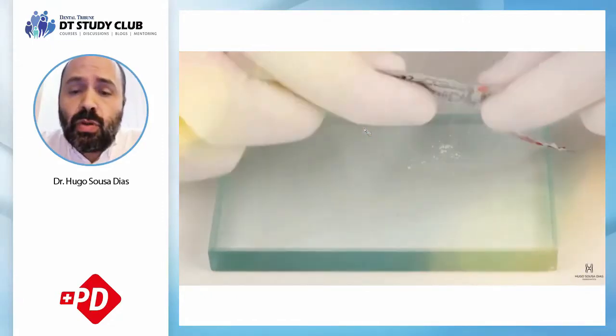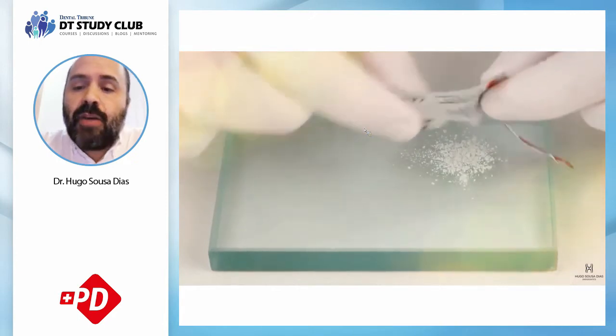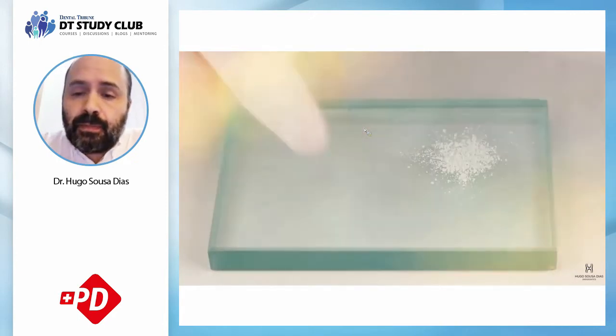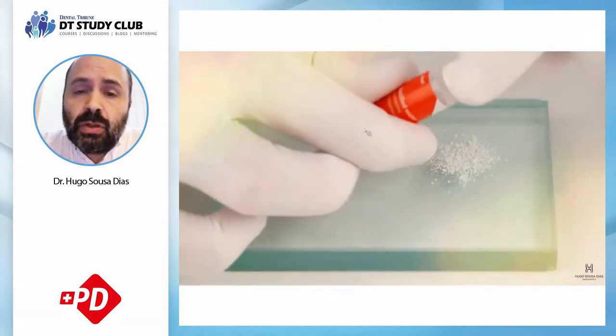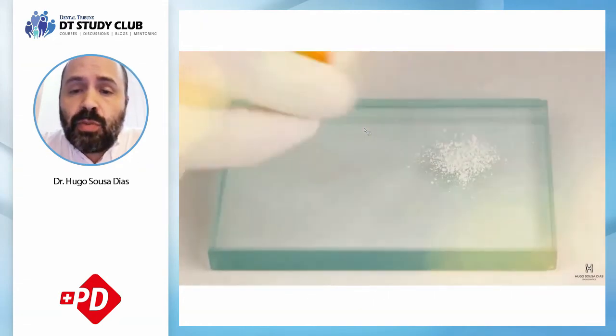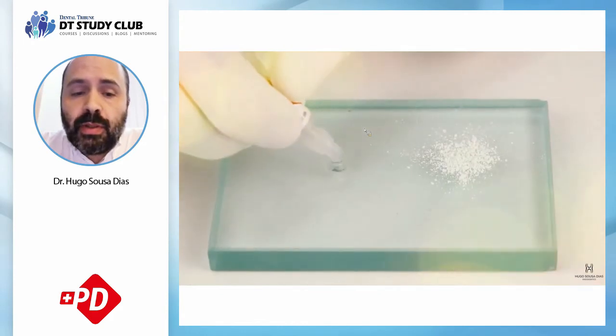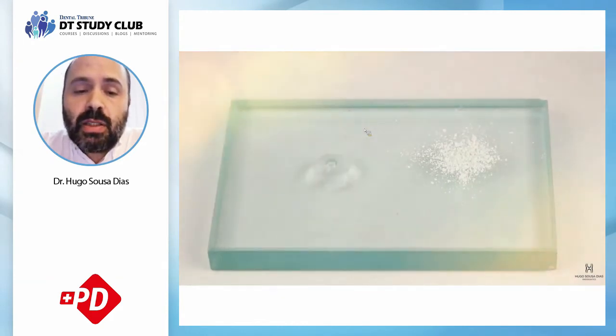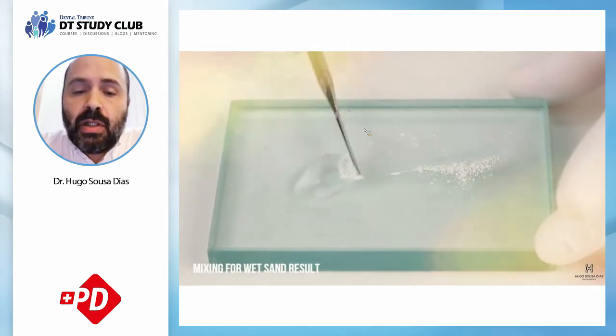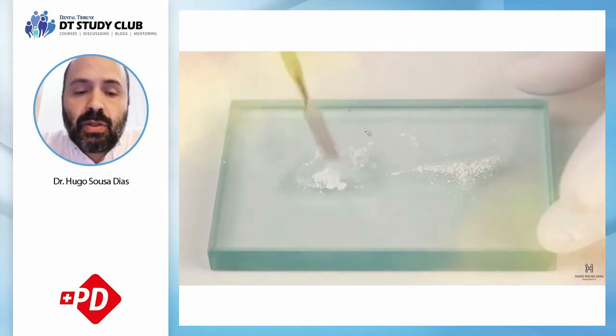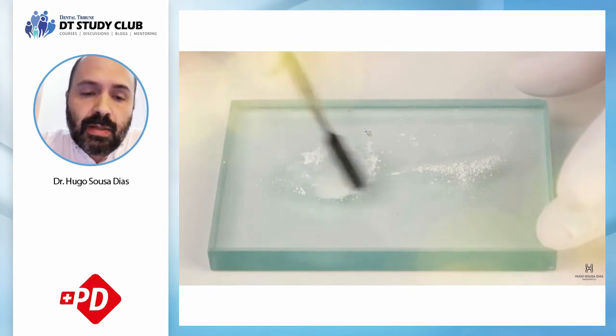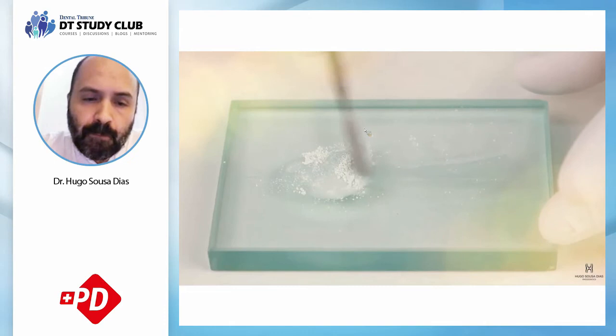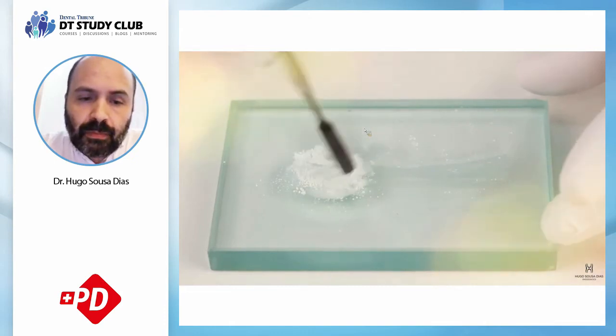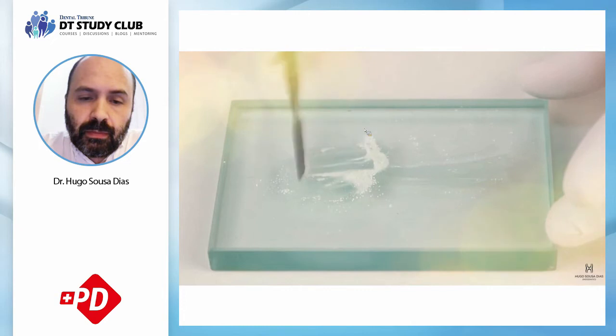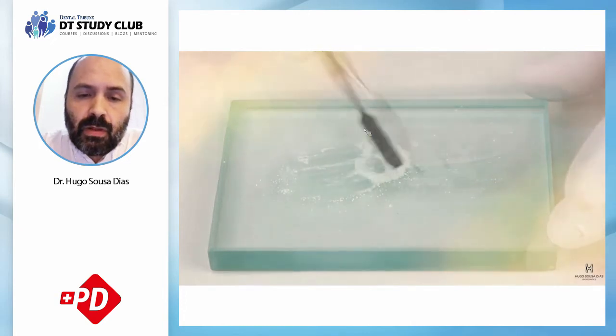I'm going to use 1 box, 1 sachet of MTA, and I'm going to use distilled water. I'm going to put 1 drop of the water, and I'm going to mix both parts, the liquid and the powder, until I achieve this wet sand result, around 30 seconds. When I achieve this wet sand consistency,